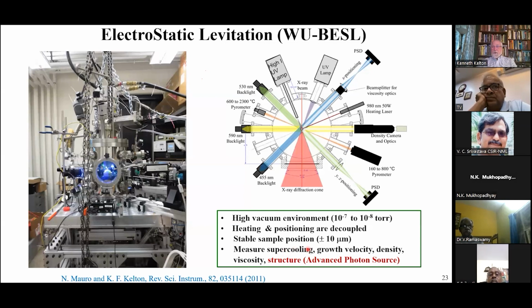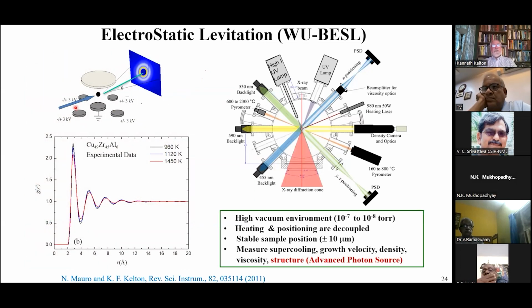With this apparatus, we can measure supercooling, growth velocity, density, viscosity, and by taking this to a synchrotron, which there's one near us in Chicago at the Advanced Photon Source, we can do synchrotron scattering measurements. And it's a very simple technique. You just have a very high intensity, very high voltage, 130 kiloelectron volt beam that punches right through the sample and gives us a scattering pattern, which we record on an area detector. This is a very good way to measure diffraction data. We've measured quite a lot of it, and it's very high accuracy, very low noise data, because there is nothing else to scatter from. So it's a very low noise environment. And so you can end up getting data that look like this, where we can follow ripples in the G of R out to very high values of R.